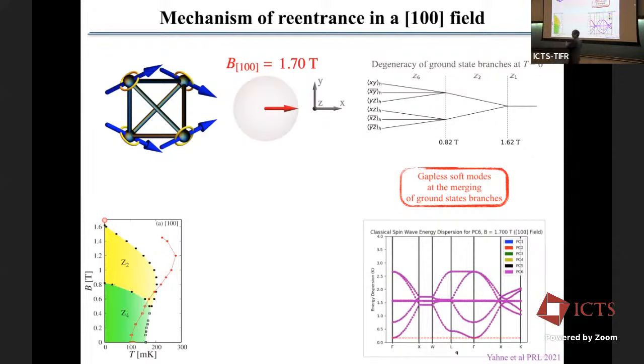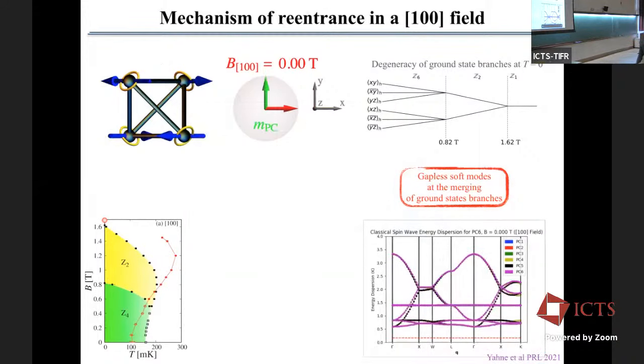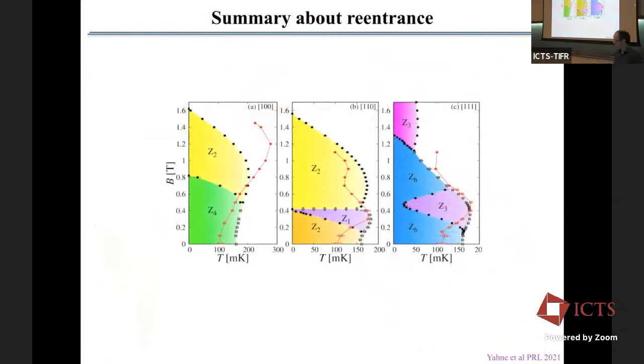And so one point here that we want to say is that when you see reentrance in a magnetic field at finite temperature, this might be the indication of a 0 temperature phase transition between 2 different phases coming from the soft modes emerging from this competition between the 2 states. And I'm going to conclude with that.